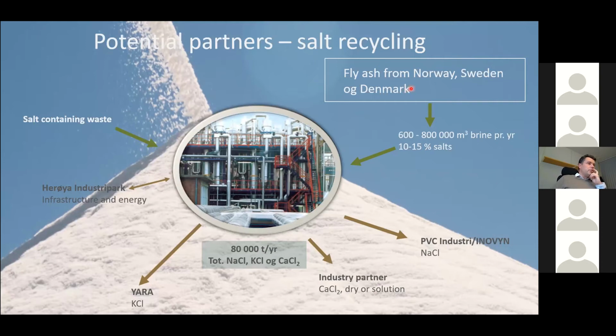The main input of salts obviously will be from fly ash, from Norway, Sweden, and Denmark. And the input will be calculated between 600 and 800,000 cubes per year, with a salt content in between 10 and 15%. And the total output just based on fly ash is in the range of 80,000 tons per year. And that is spread over sodium, potassium, and calcium chloride.